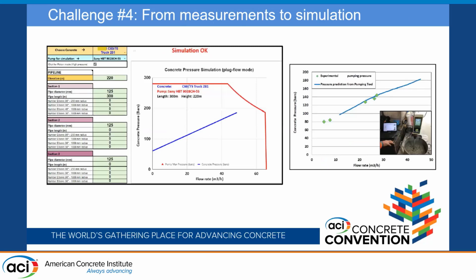So this is what the prediction tool looks like. You can see the red line is a given pump. Up at the top, we picked the C60/75 mix design, which we tested through the tribometer. We had the results, and then we said we're going to push it through the HBT 9028CH pump. We plug all that data in, the power requirements, the shaft size, all the information that's relevant to the pump, in the background. Then in the prediction tool: what is our elevation? 220 meters. What's the pipe diameter? 125 millimeters. And then your full length is 300.